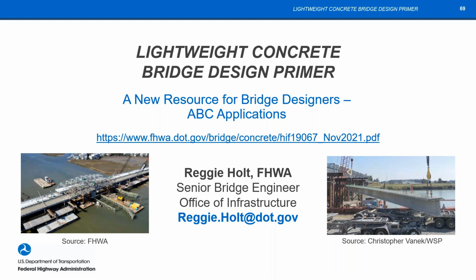So we did see the Benicia Martinez Bridge is doing fine. There's no sag on that one. The deflections are not unexpected. So we do have long span bridges. And I didn't mention it, but in Norway, there are 3 cantilever constructed segmental box girder bridges that are 300-meter spans, almost 1,000 feet long. And they use lightweight concrete in their main spans. So they've been able to deal with it if you construct it appropriately and know what you're looking at and use the right values. You can build those bridges so that deflection is not a problem. You will have more live load deflection because you have a lower modulus that's coming from that equation. But typically we're still within range. We don't exceed anything there.